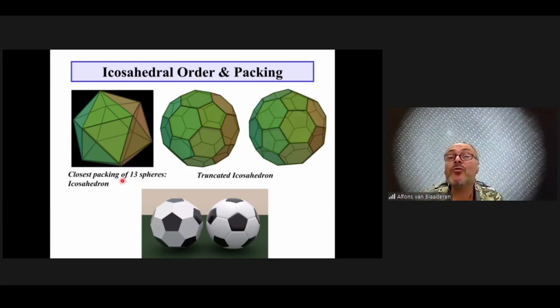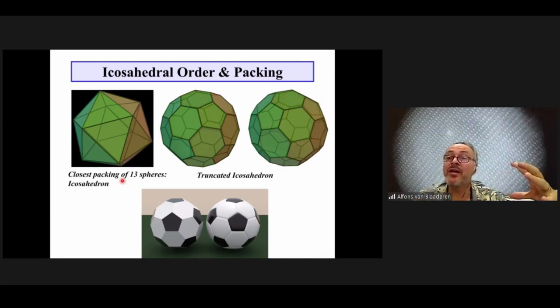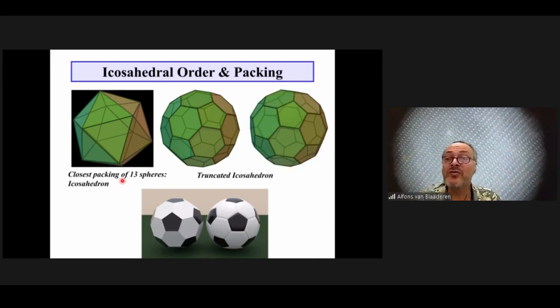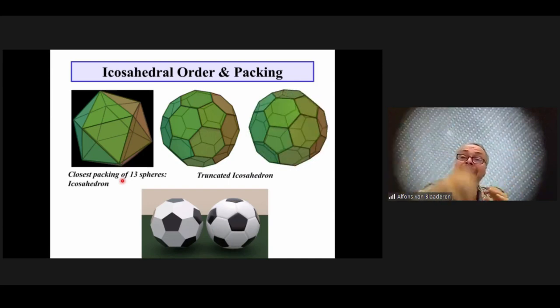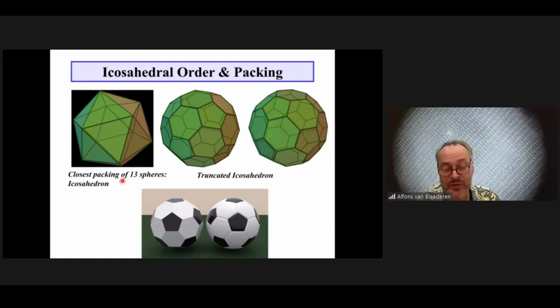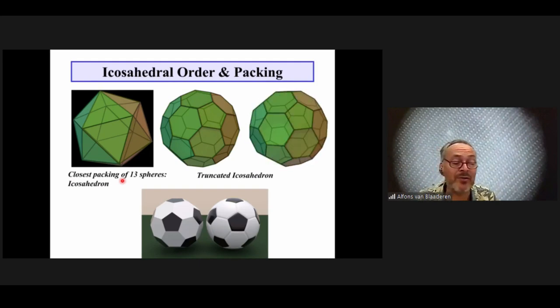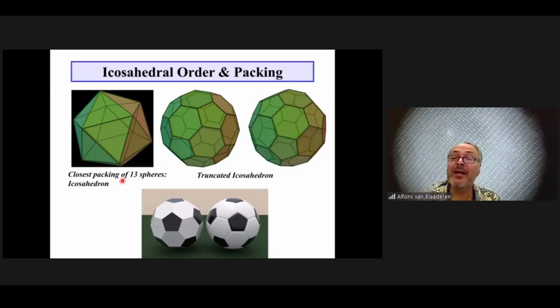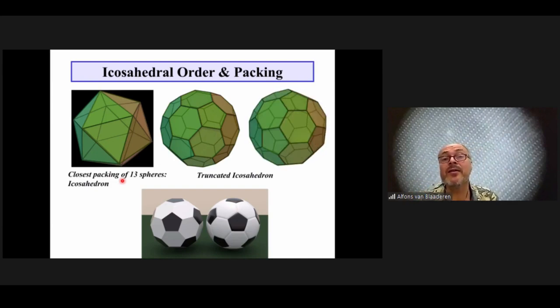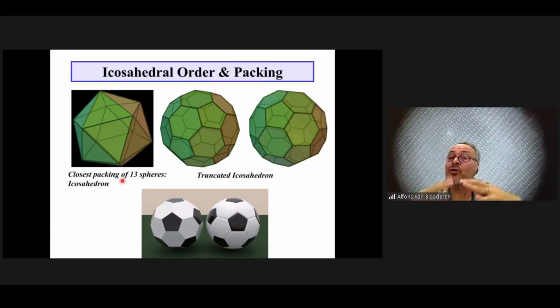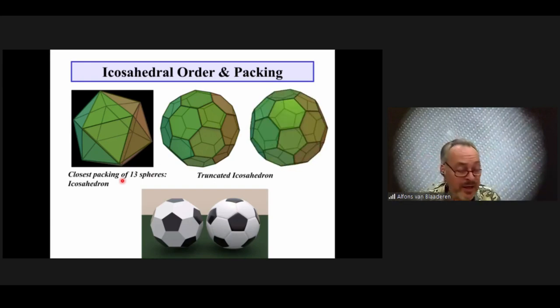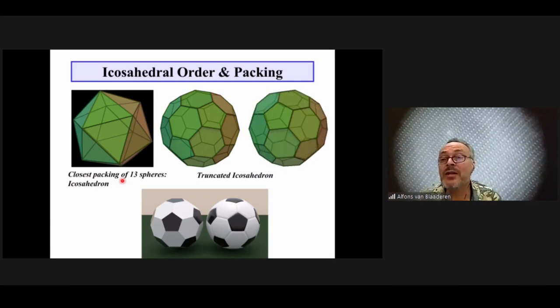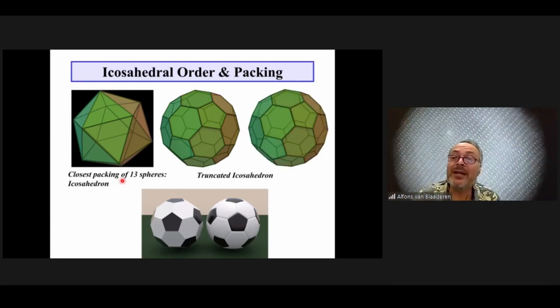What was not known is that this argument also holds for hard spheres until you have about 9 layers of particles. So when you have on the order of 100,000 particles, then the free energy of packing is still dictated by the fact that icosahedral symmetry can have a lower packing fraction. If you continue to do this, to make this an infinitely large structure, then you lose out, because the volume fraction of these icosahedral packings is only 68% and not 74%.